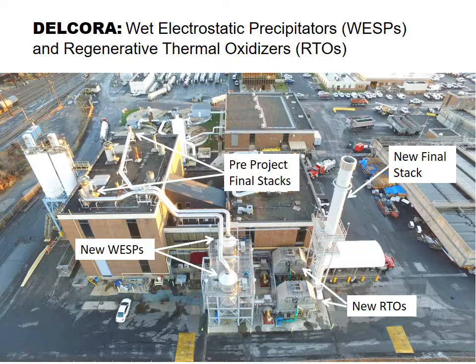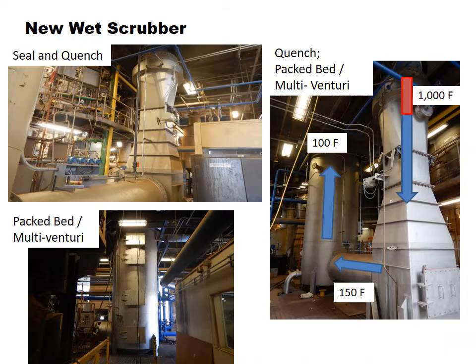Existing stacks right here and here. We piped them over to some new wet electrostatic precipitators. The precipitators were put in not necessarily to meet the regulations but to protect the media. Here's the RTOs. We put a new stack in here. So we also, inside the building, to get a capacity increase, replaced the scrubber. We put a Quench and a multi-venturi scrubber in there, so gases come out of the furnace about 1,000. We cool them down with the Quench to about 150, and then through a packed bed and multi-venturi scrubber, they come out about 100 degrees.